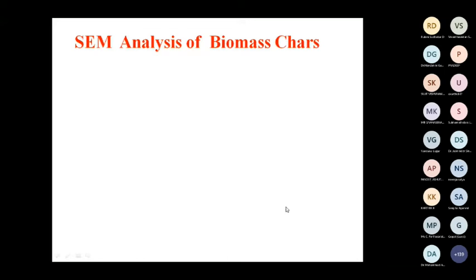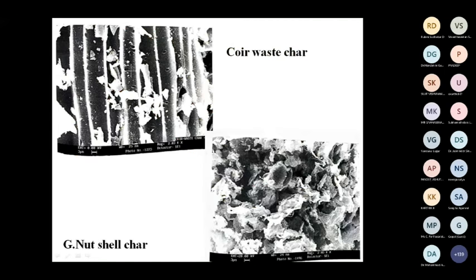See the SEM analysis. I am only showing the picture. See the coir waste, a lot of valleys, so complete combustion of the entire surface area is possible. The total surface area is available for combustion here. Coir waste, you see a lot of valleys. This is a 2000 magnification SEM of coir waste char, whereas in groundnut you can see some part of melting. All are prepared at 900 degrees.